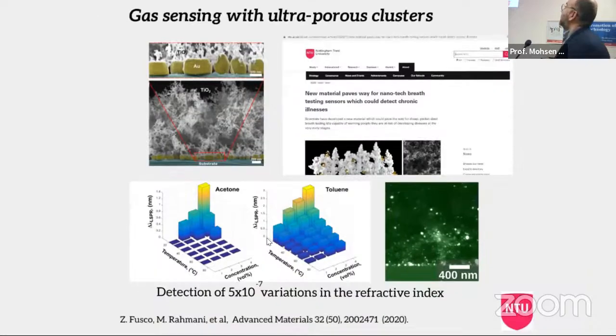So here is where we also developed this material. These porous films are 96% porous titanium oxide and only 4% material, and we managed to increase the sensitivity significantly because we increased the sensing volume. I'm not going to bore you with the physics again, but the result is that with this technique we managed to detect not only the existence and type of different gases, but also their concentration. So what is the application?